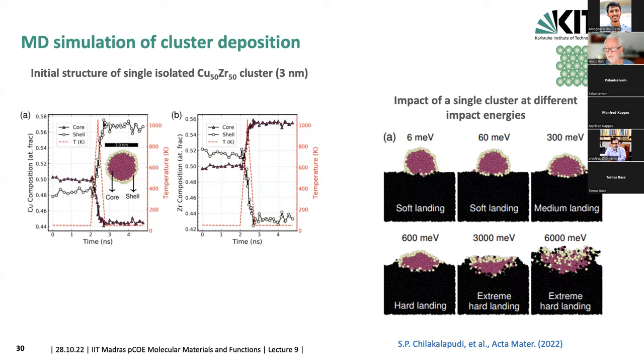Then he also looked at what is shown on the right side, the impact of a single cluster at different impact energies. And you see the difference between soft landing, medium landing, and extreme hard landing, where in the latter case, you see that the atoms are almost completely intermixed with the substrate, whereas in the low deposition energies, we keep the clusters intact. And you can imagine that all plays a role in this behavior.